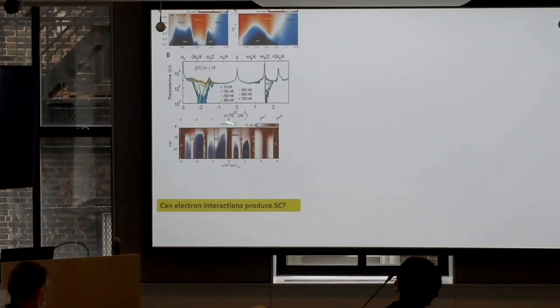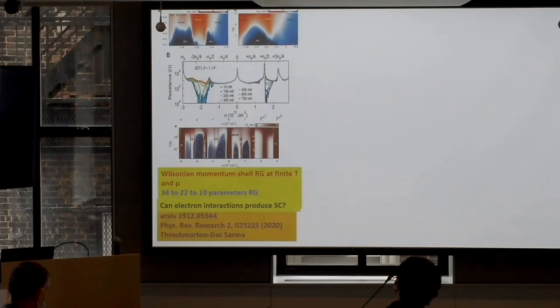This experiment was very instrumental in developing my intuition for it. In fact, this was presented at a KITP conference. And I immediately said that I think this is telling us that it's all superconducting, except the superconducting phase is preempted by strong correlation and insulating phases. But since we are theorists, I had to do some RG calculation showing that we can actually calculate electron-electron interaction in this superconductivity. When you do RG in a complicated system, you find superconductivity everywhere.